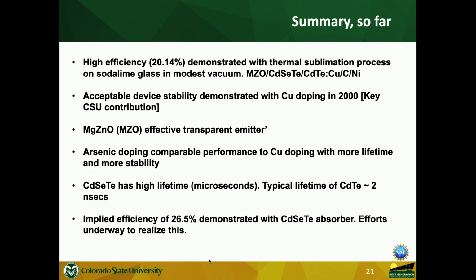CdSeTe has high lifetime, in microseconds. Typical lifetime of cadmium telluride is in the 2 nanosecond range. Selenium improves the performance of the photon-generated electron-hole pairs and lasts quite a bit more time than it would in cadmium telluride. Now here is where it gets interesting.